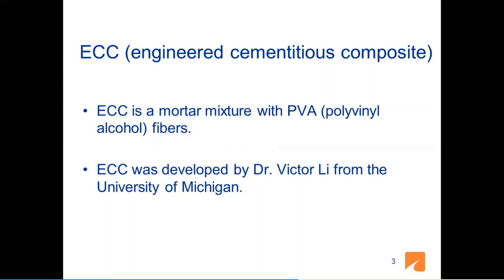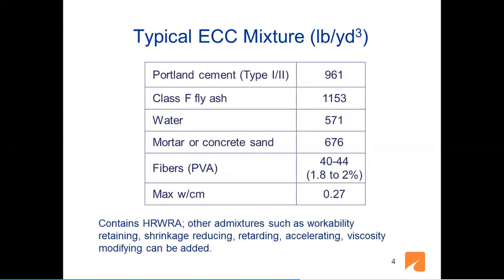ECC is a mortar mixture with PVA, polyvinyl alcohol fibers, and it is a fiber-reinforced concrete. The reason we use it is to control cracks in our concretes. ECC was developed by Dr. Victor Li from the University of Michigan. A typical ECC mixture is shown here in pounds per cubic yard. It has high amounts of Portland cement, Class F fly ash, water, and the initial mixes had mortar sand, but because of availability in Virginia, we are using concrete sand as well.